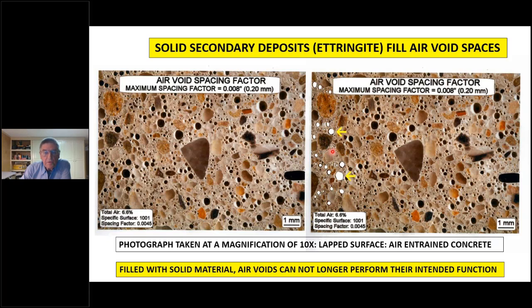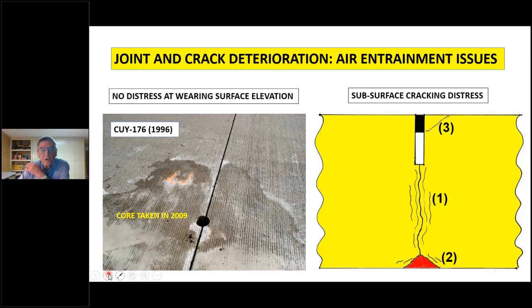So you'll see that the air voids in and around the joint are filled with the secondary deposits, which primarily are ettringite. We think of ettringite as a destructive form of attack, but in this case, the ettringite in the air voids is innocuous, and it's very, very common. In fact, it's unusual to not see it. So we look at the cores that we took where there was no distress on the wearing surface.